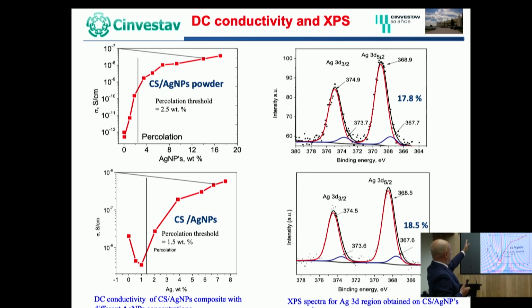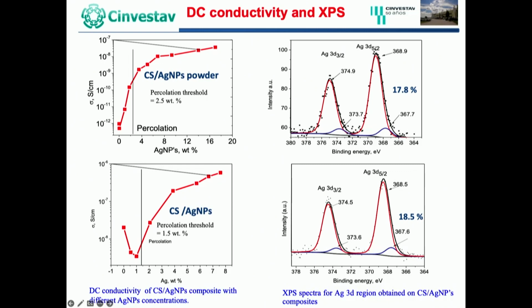Well, look at the two graphs on the left-hand side. You see the percolation threshold, more or less around 2.5. We have a special software. You can construct two tangent lines and there are different methodologies to find the geometric approximation of where the percolation threshold is on the upper hand side. On the lower hand side, look at the behavior is slightly different, but actually we can bring the percolation 1% lower. How to achieve that? We manipulate the reaction very simple, recognizing that silver is a metal, and we're using the metabolic machinery of this bacteria, which is not a very aggressive reducing agent, that initially we thought it was a drawback, but in the end it turned out to be a good thing.